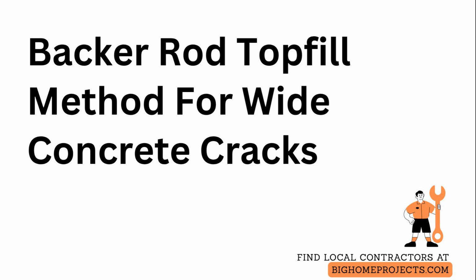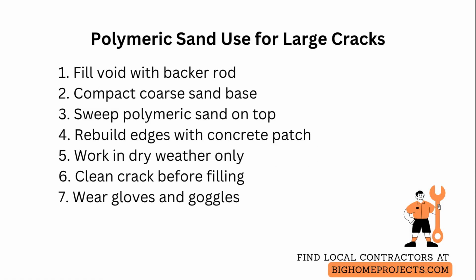Polymeric sand can work for narrow joints, but it is not a reliable standalone fix for large or deep cracks in concrete sidewalks. For cracks wider than about 1/4 inch or deeper than 1 inch, we recommend a two-step approach that starts by filling most of the void with an inert filler such as a closed-cell backer rod or compacted coarse sand to create a stable base and limit how much polymeric material you need to place at the surface.